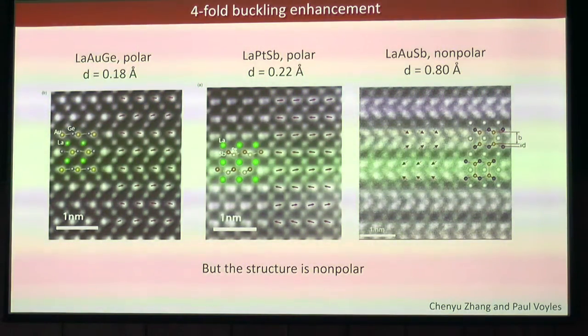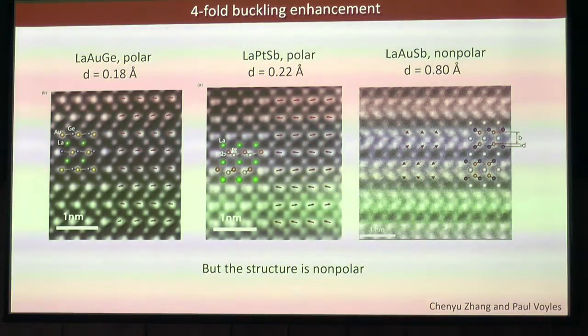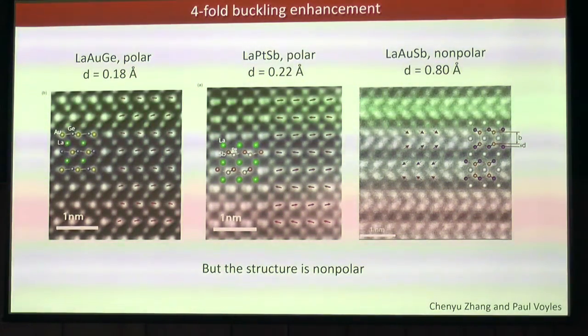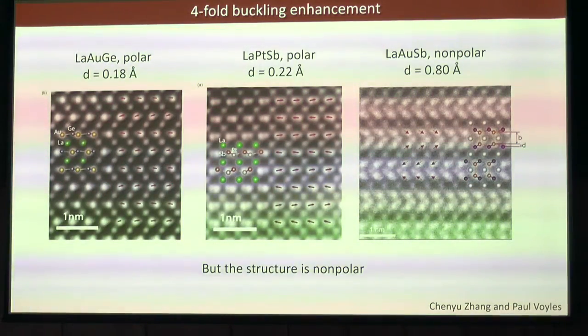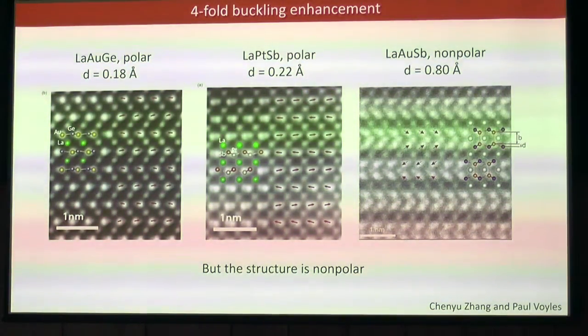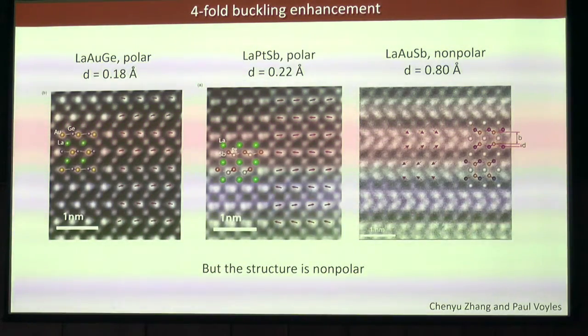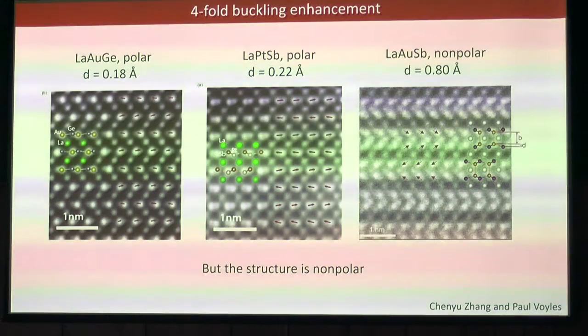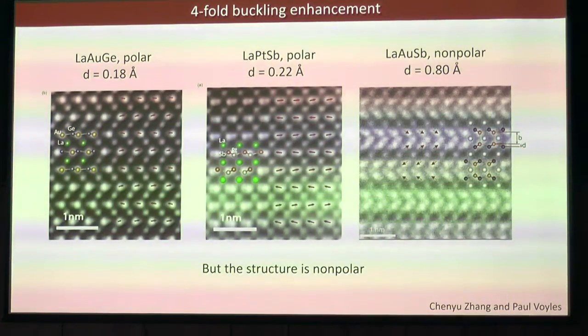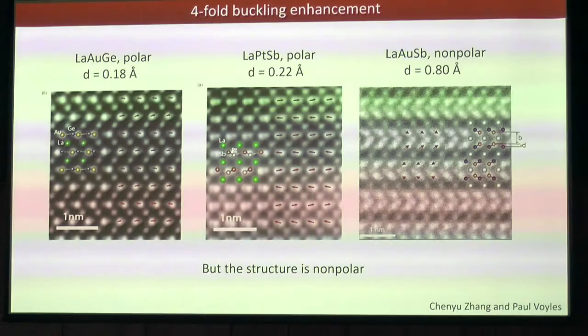Yeah, so I think this is a great example of the materials by design paradigm. But I'm wondering, when you were looking at the doping of the gadolinium, that was really looking at it from experiment, right? Yeah. But why not do the calculation first, of the band gap or density of states as a function of the buckling, and see what opens the gap? The real reason is that we were interested in the magnetic part, so we wanted to do the gadolinium doping anyway. Okay, but still, it seems like you could put in the buckling and see if that opens a gap or not, and how much it requires. And if it never opens a gap, then you wouldn't need to do the experiment if you trust the theory. But